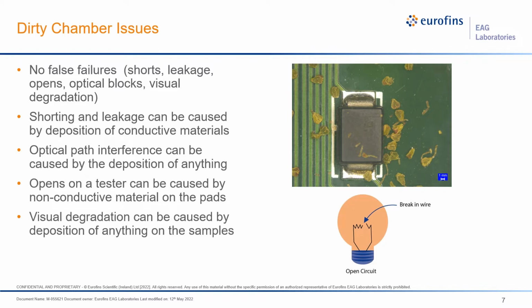And the reason you don't want to have dirty chambers is you don't want false failures where the contamination can cause you issues like opens or shorts, optical blockage, or even just making your part look visually not look good. So that can be an issue in certain types of samples as well. The shorting and leakage issues can be caused by deposition of conductive materials.